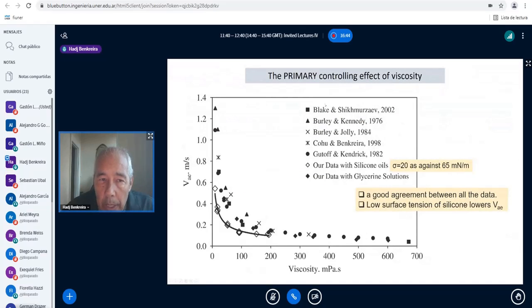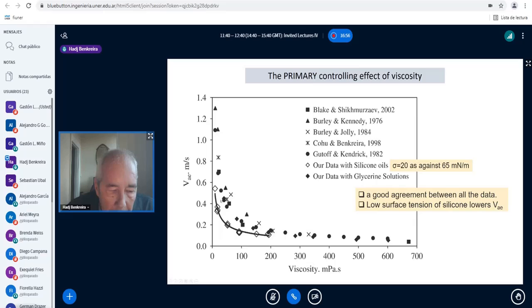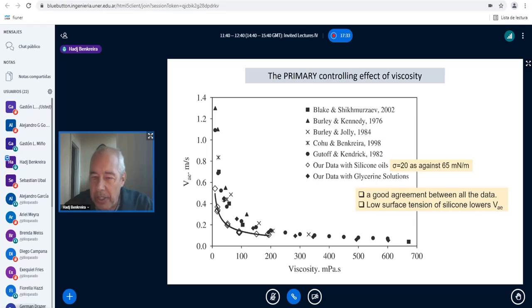And the other important thing, when you look at other parameters, the only other parameter that affects the air entrainment speed is surface tension. Surface tension decreases the air entrainment speed substantially, particularly at the lowest viscosity. But grossly speaking, it is not really very important. The important variable is viscosity. And the reason is that you cannot change surface tension by much. The majority of fluids will have a surface tension near, say, 60, and even if you go low, you will never go lower than about 20 or 25. So the change in surface tension is not as important as viscosity, and that is the reason why the controlling effect is in fact the viscosity.